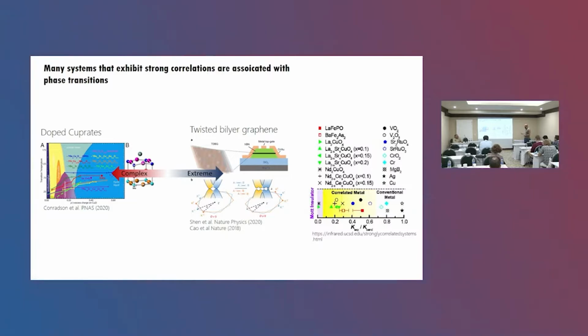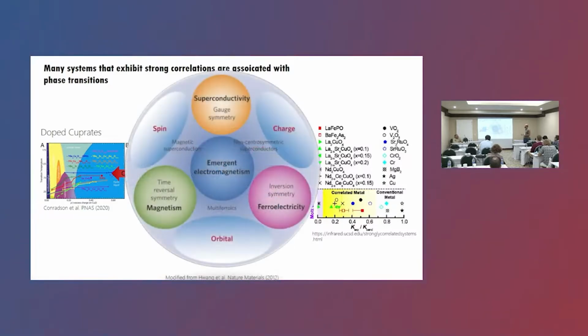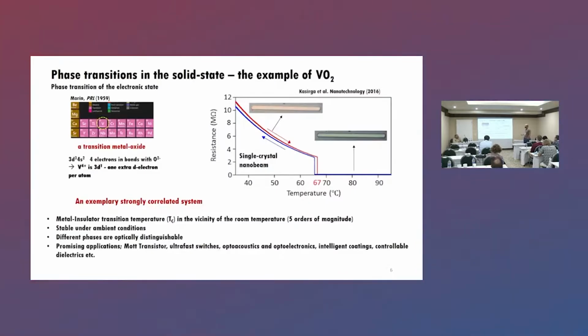So here I'm going to focus on VO2, where these correlation effects lead to the phase transitions that I already mentioned. I spent quite a lot of time with VO2, so I'll continue my introduction with VO2. Vanadium dioxide is a very simple transition metal oxide, which exhibits a phase transition at about room temperature. It goes from being an insulator to a metal if you increase the temperature, and a structural phase transition is associated with it.